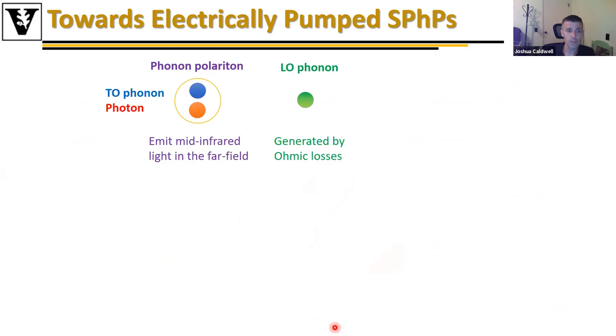Well, one of the things that this provides us is, if I look at the phonon polariton mode, these can emit into the far field, as I showed you through thermal emission, because they're transverse fields and they're coupled. It's a coupling of a photon with a transverse optic phonon. However, these cannot be electrically stimulated because the fields are orthogonal to the longitudinal fields of a free carrier-based system, right? However, LO phonons can couple through an ohmic loss, and therefore we can stimulate LO phonons via such a